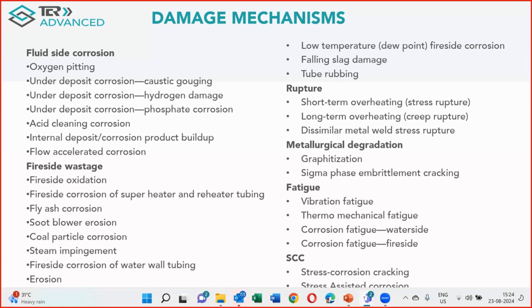Then there are rupture kind of failures, short term and long term failures, which mostly occur because of operational issues. And then you have graphitization and sigma phase embrittlement. Now, these graphitization problems I have seen in boilers in many locations where carbon steel is supposed to be operated at less than 400 degrees centigrade as a skin temperature. But if your skin temperature increases to 425 plus, then carbon steel is subject to a problem called graphitization, and it can really cause a brittle fracture of the component.